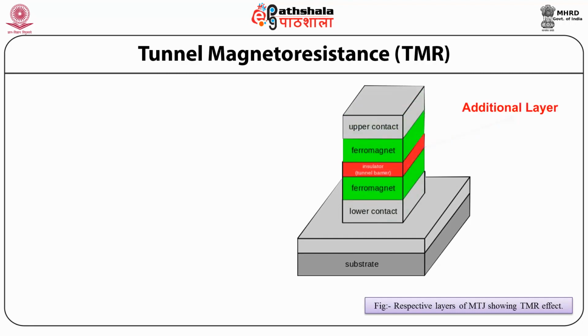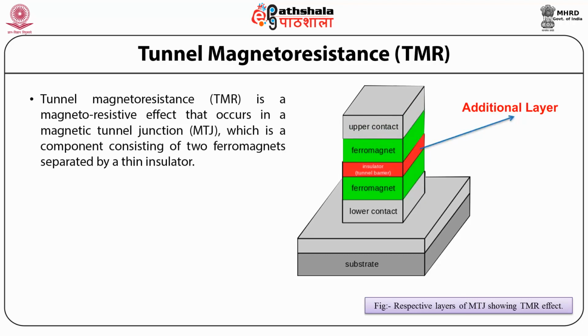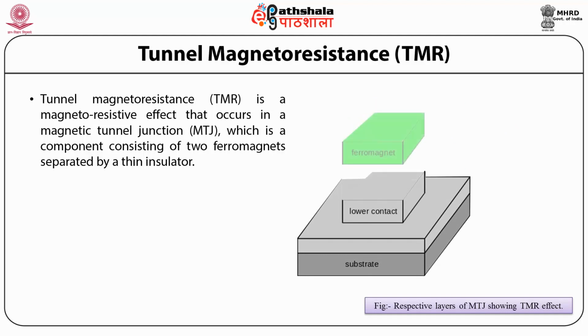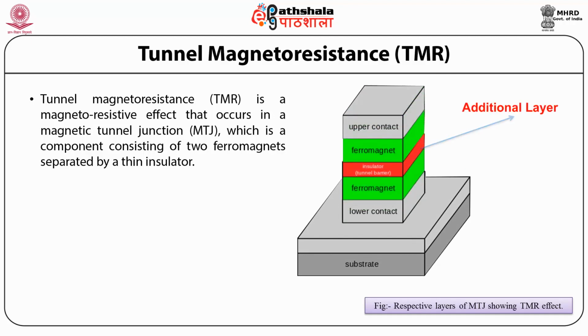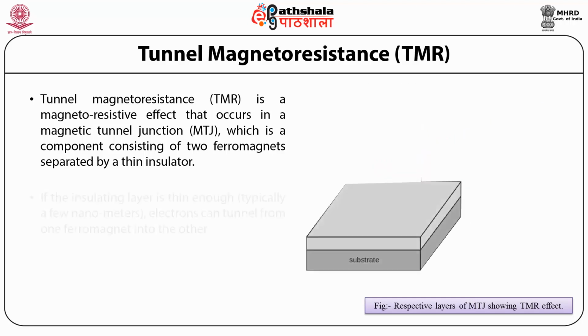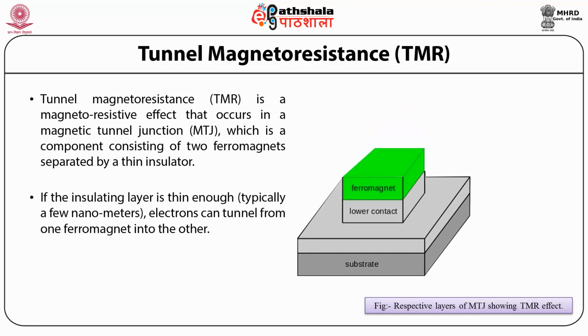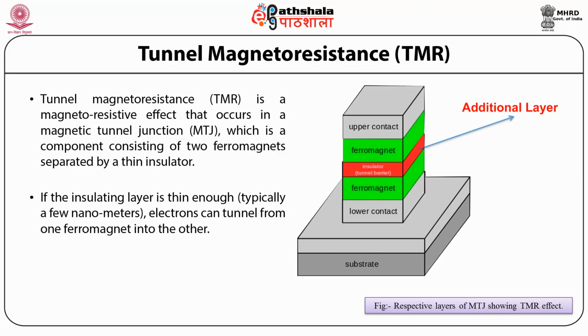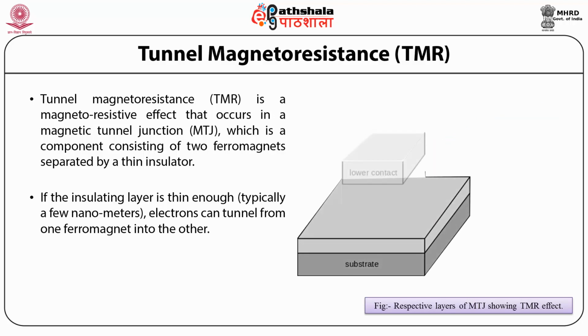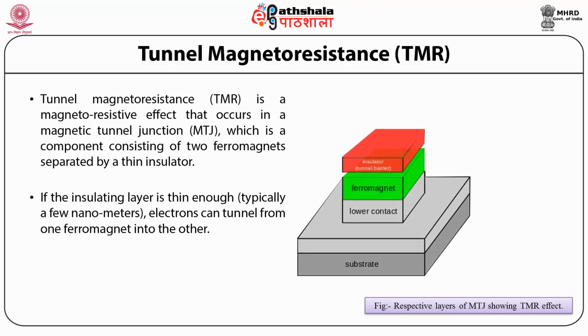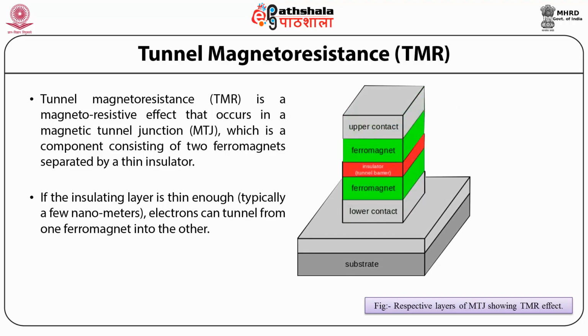A schematic of a tunnel magnetoresistance has been shown clearly in the figure. Tunnel magnetoresistance, TMR, is a magnetoresistive effect that occurs in a magnetic tunnel junction, which is a component consisting of two ferromagnets separated by a thin insulator. If the insulating layer is thin enough, typically a few nanometer, electrons can tunnel from one ferromagnet into the other. Since this process is forbidden in classical physics, the tunnel magnetoresistance is a strictly quantum mechanical phenomenon.